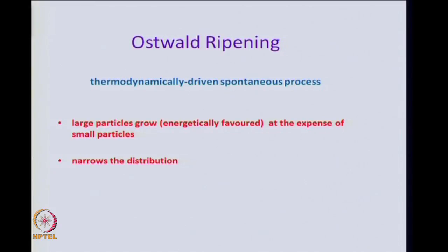method. In the Ostwald ripening method, it is basically considered to be a thermodynamically driven spontaneous process. In this process, large particles grow at the expense of small particles. These large particles are energetically more favored, and hence the small particles in the vast number of nuclei which form change into or grow into these large sized particles. So, they attach themselves to the larger sized particles, making them even larger, and by this they reduce the surface energy, because smaller sized particles have more surface energy. And so, the larger sized particles are energetically more favored.